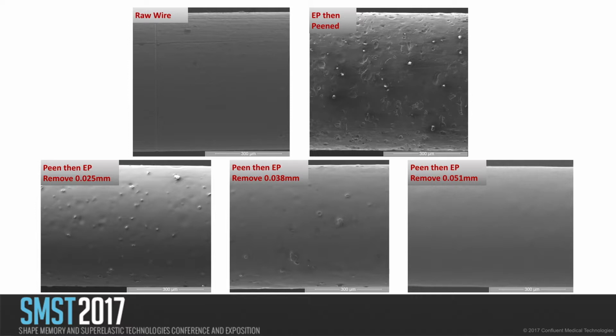One thing to note, with all of these states, we performed nickel ion release testing, and none of the tests showed up positive or unacceptable for nickel release into the body. So even in the worst state, where you have peening media embedded in the surface of the material, we still didn't see appreciable levels of nickel ion release.